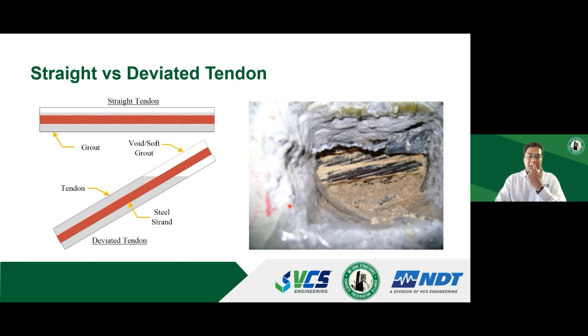So when it comes to failures and segregation of grout or grouting defects, the profile of the tendon matters a lot. If we are talking about a straight profile, there are high chances that when the grouting operations are being conducted, the tendon will be uniformly coated with the grout material, which is of high pH, highly alkaline in nature, and that high pH or passivity can protect the steel from future corrosion. Whereas if you have a deviated tendon or an inclined or vertical tendon, you tend to see grouting defects being more prevalent, especially because some sections of the tendon could be completely exposed, whereas others are completely grouted. In the completely exposed sections of the tendons, you have no protective oxide layer being formed because of the highly alkaline grout, and that's why you have higher susceptibility to corrosion and eventual failure in those uncoated sections or unbonded tendons.